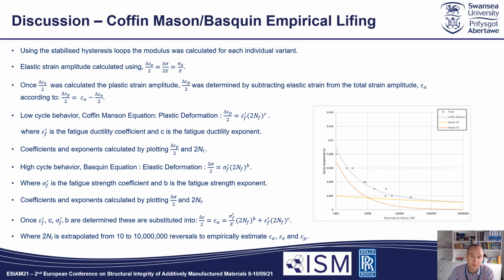Then we bring in the Coffin-Manson equation, which is the plastic strain amplitude is equal to the fatigue ductility coefficient multiplied by 2 times your fatigue life to the power of a fatigue ductility exponent. These coefficients and exponents can be calculated by plotting the plastic strain amplitude across your fatigue life values, times them by 2, and then using log-log axes.